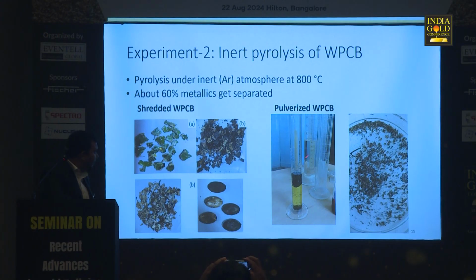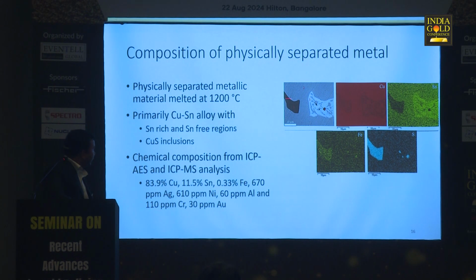Similar exercise recently we have also done for the pulverized PCB, because some of the plants use the pulverized PCB, and you can also heat it at 800 Celsius and then do the density separation, and you can separate the metallics from there as well. So then after pressing, this was melted, and now what we have essentially is a copper tin alloy.